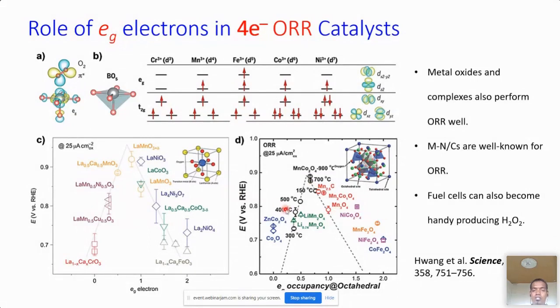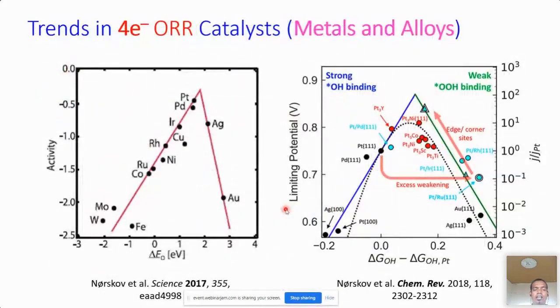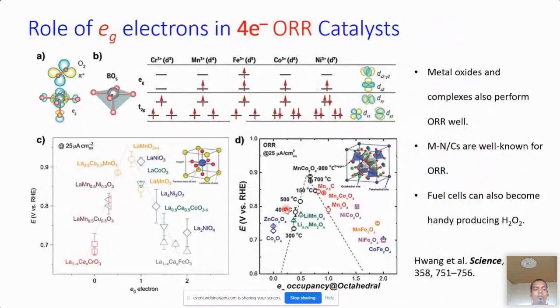This will help us design and fabricate efficient fuel cells, which can help generate power back from the hydrogen generated from water electrolysis. So we have theoretical modeling which can predict the activity just by plotting the limiting potential with the free energy changes of the intermediate steps, and we also have this interesting correlation between EG electron occupancy and the type of compound formed.